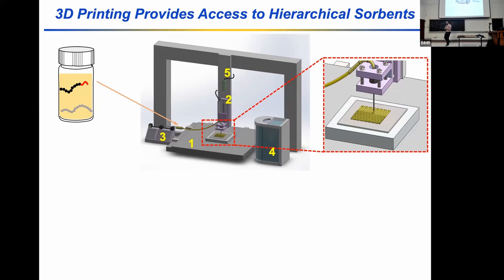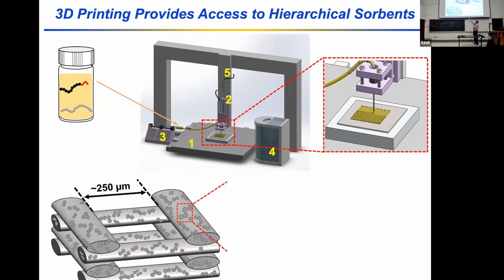And so the way this technique works is it uses that same humid air vapor induced phase separation technique. And now instead of taking the formulated ink and film, we put it into a syringe pump that dispenses that solution from the top of a Z-axis controller. And then our substrate, our membrane support, sits on this XY controller. And so we're able to extrude this solution into a humid environment. So it's going to go through that phase separation process as we're controlling the macro scale structure, right? And so the dream is that we'd be able to extrude filaments that have nanoporosity like the membrane sorbents we just talked about, but we're able to purposely program in these large co-channels between the filaments.